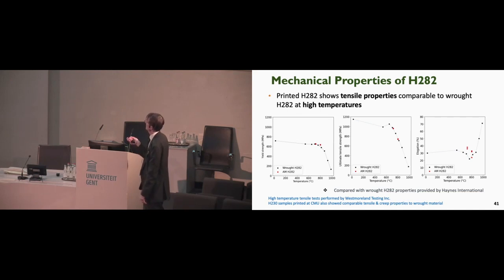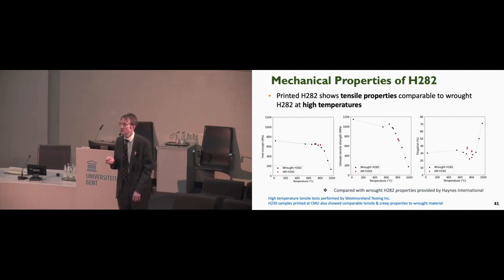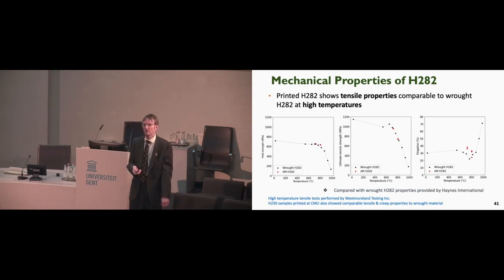And so this is the yield strength as a function of temperature. This is the ultimate strength. And then this is the ductility. And so the black dots are data supplied by Haynes International, standard material. The red dots are from our tests on our printed Haynes 282. And the good news is, basically, we're seeing the same properties.